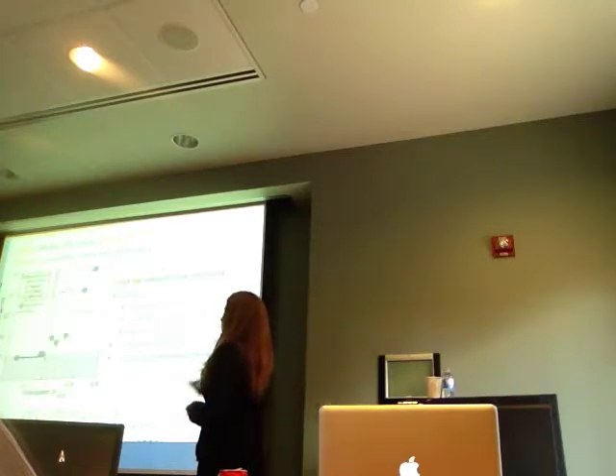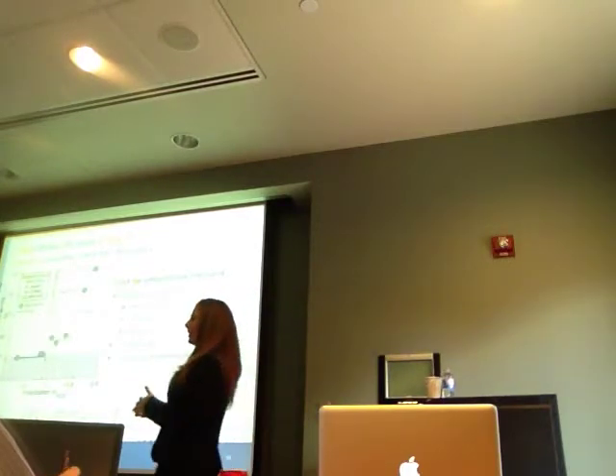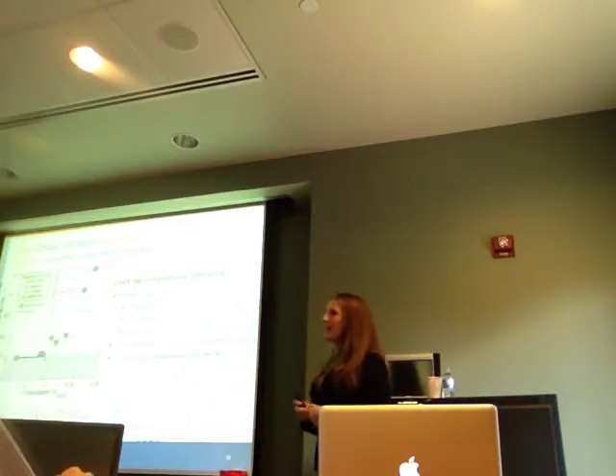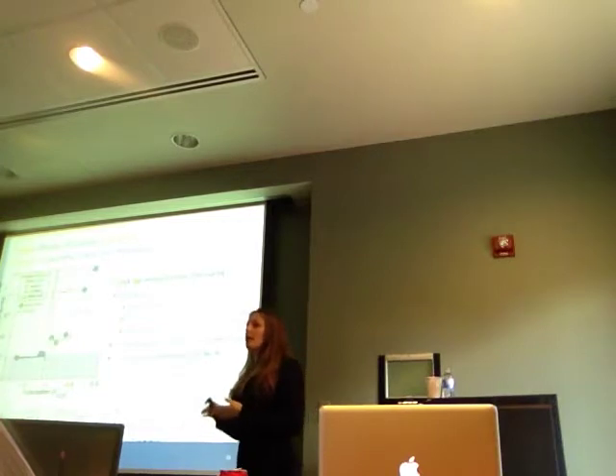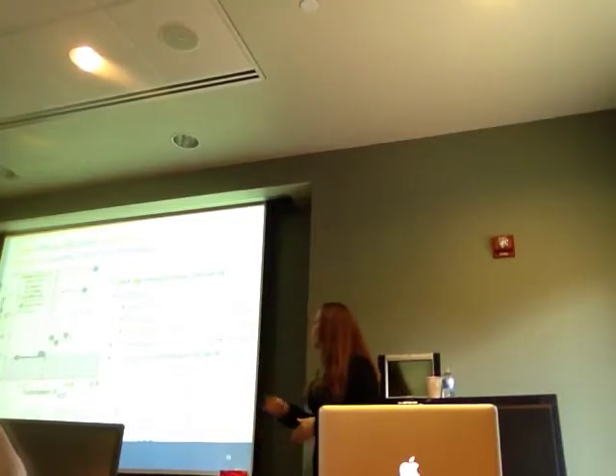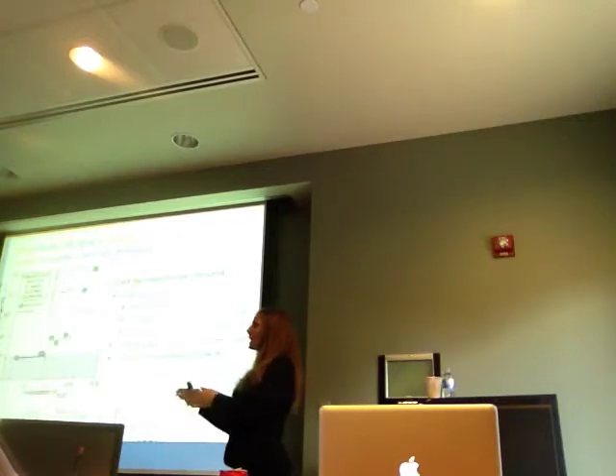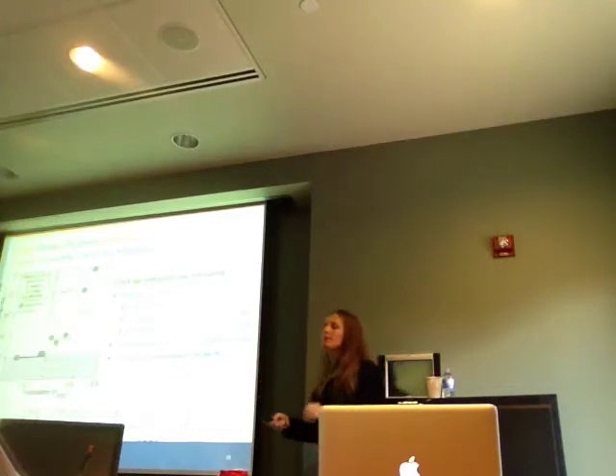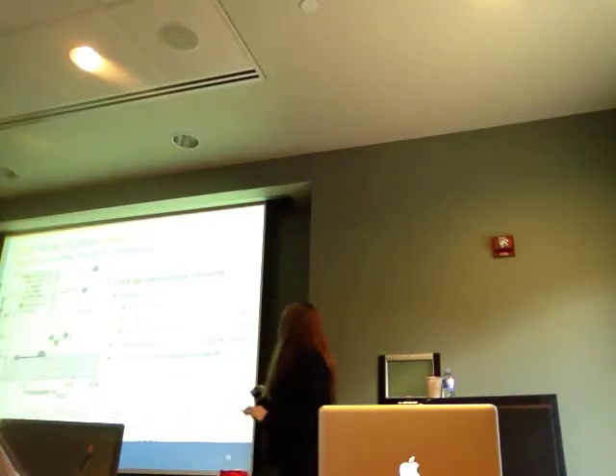So once we established that that was occurring in our crack tip, because we were getting intergranular corrosion, we could use the dissolution current density at the tip, which was given to us by our intergranular corrosion rate, and our passive current density on the flanks, which is our matrix, to predict the ohmic drop that was occurring from the bulk applied polarization to your cracked tip polarization. So knowing that difference, you can predict what the potential is at the tip, and you can also predict the pH at the tip.